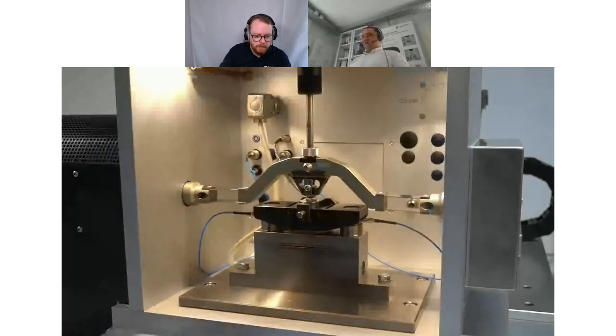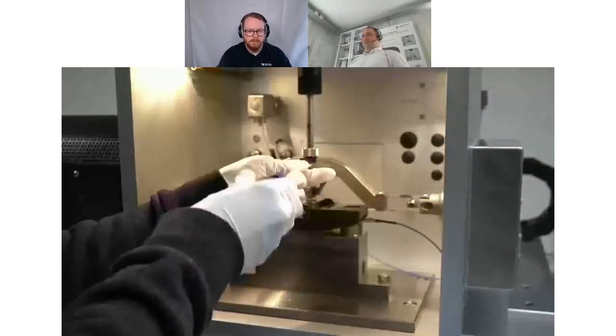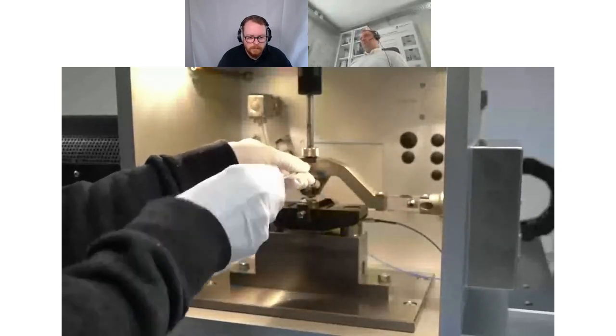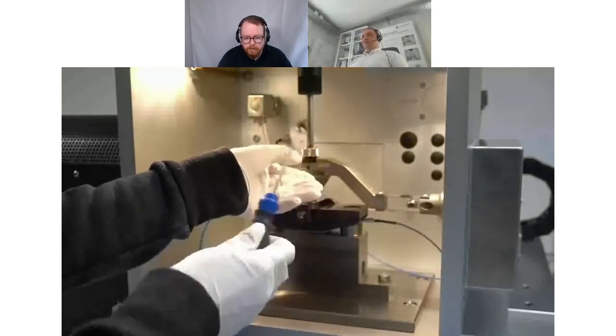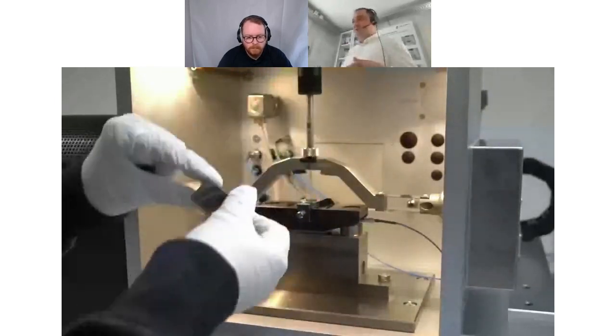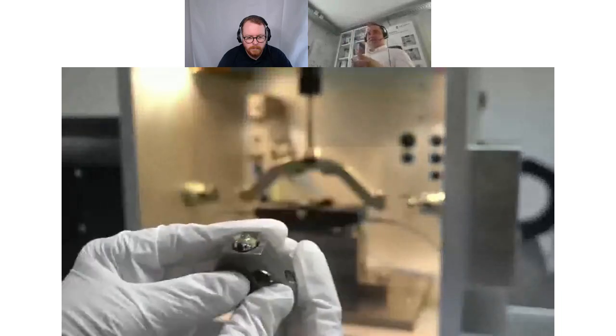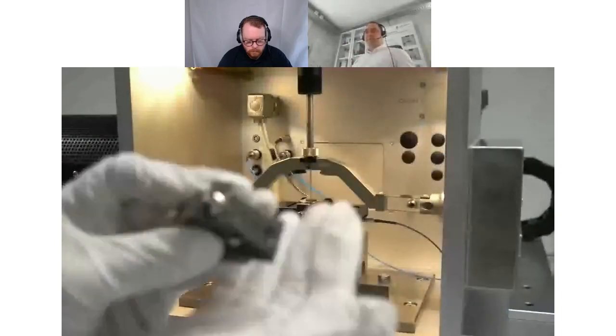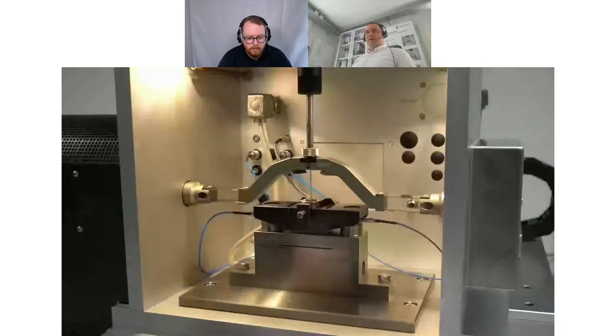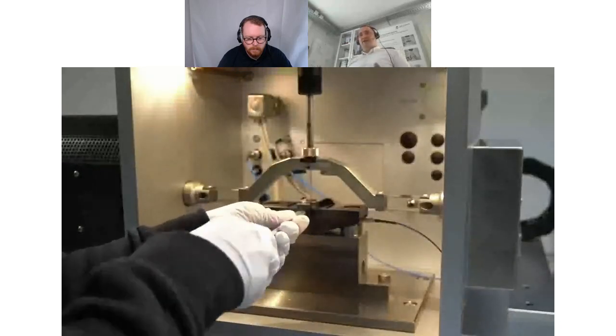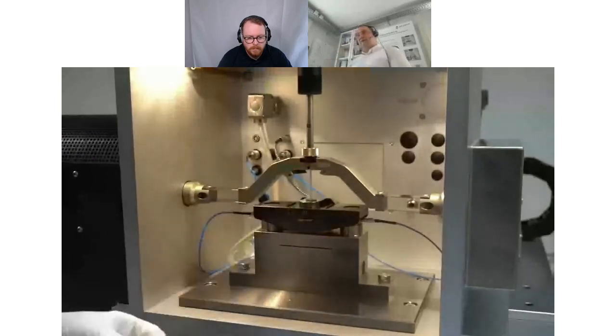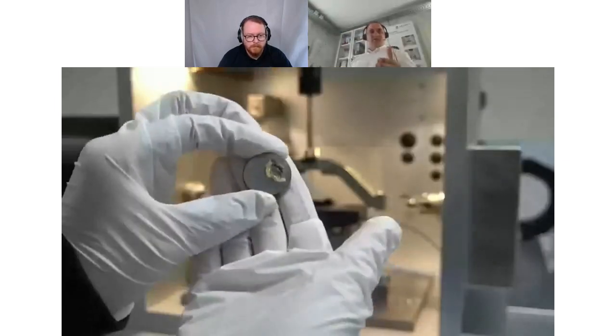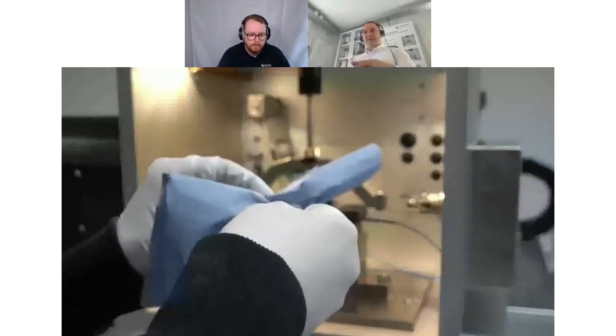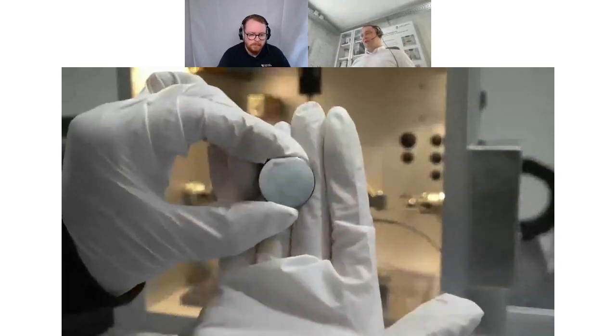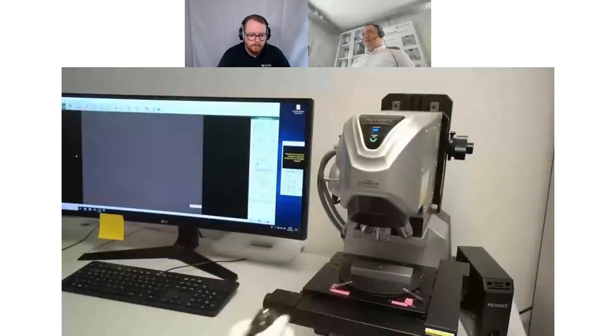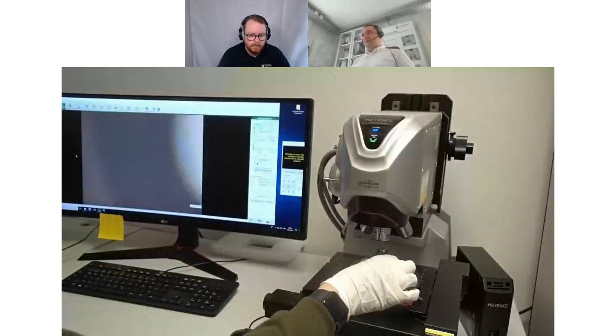After the test, you uninstall then the samples and clean them with a wiper only. So you don't have to clean them in the ultrasonic cleaner, because sometimes you also have tribochemical layers on the surfaces, and we don't want to remove them, because we want to have them on the microscopic image so that we can judge after the test if there were reactions, which kind of reactions, and if the entire surface was coated, for example, during the test by those tribochemical reactions or not, or if we have clean metal to be seen on the microscopic image.